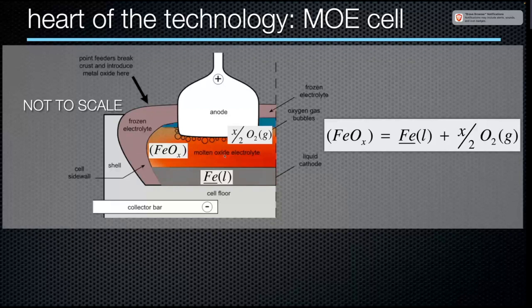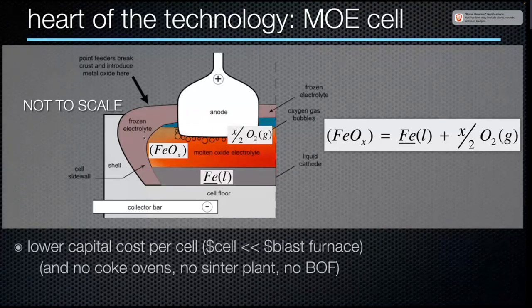So you could have non-uniform temperature distribution here so that in between the electrodes, it is highest temperature. And on the edge, it's low temperature, low enough that the electrolyte becomes a solid. And so you basically have what they call the skull. So this is liquid electrolyte inside a frozen skull of itself. And so that's the idea of the molten oxide electrolysis.